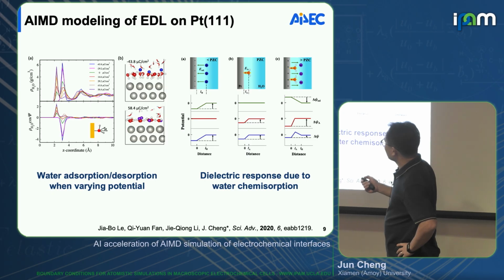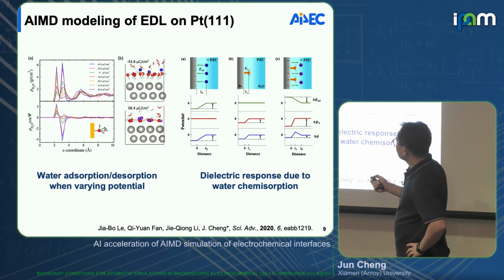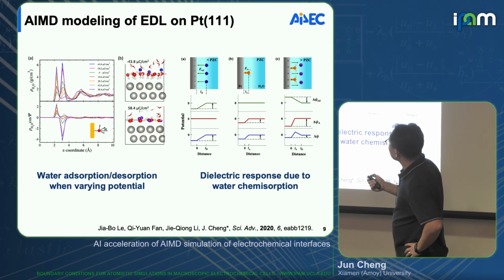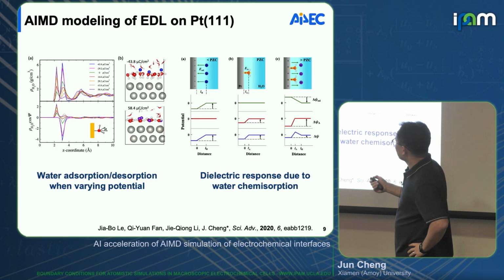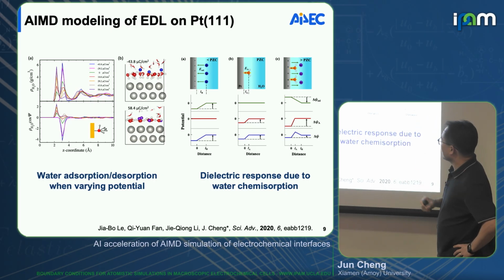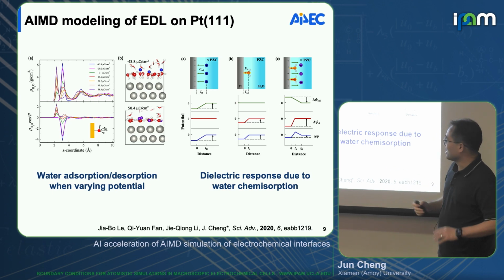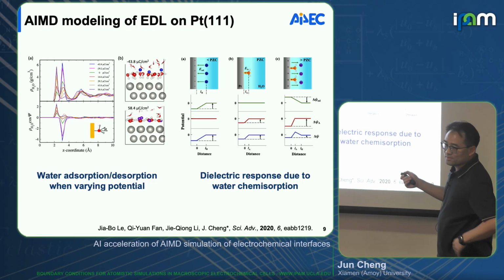It's a neutral interface. We put the counter ion in this solution. In this case, it must be fluorine, or yeah. Then the positive charge will go to the platinum surface. Then the ion will take, that's an anion, right? So that's the electronic ground state. You have a natural electron separation. But anyway, they will build up this compact Helmholtz layer in our ab initio molecular dynamics model. So you can see here a positive charged surface. You have many water molecules chemisorbed with oxygen really touching the platinum.